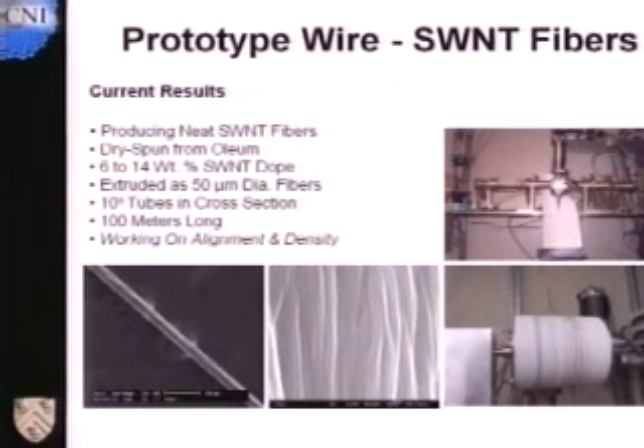You'll end up with a nice fiber, and it has some residual microstructure that is limiting both its mechanical and its electrical properties at the time being. This is nowhere near where we want it to be, or where we think it can be. These are running about 1% of the conductivity of copper, about 1% of the strength, 1 to 10% of the strength that we expect. But we are routinely producing fibers that are, say, 50 microns in diameter. These have a cross-section of approximately 1 billion tubes. And so we're currently focusing on the connectivity of the subdomains and improving the crystallization properties of the material.